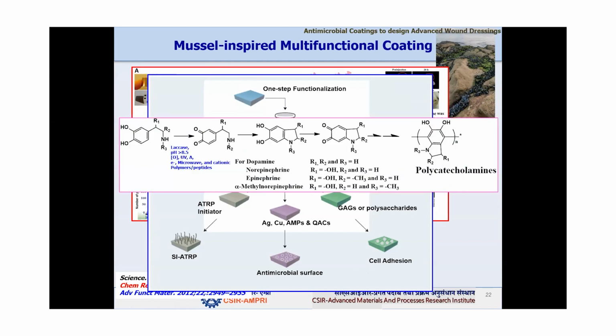And this is a simple mechanism of how dopamine and the related compounds polymerize and we get polydopamine or other related polymers. So this is the one part I have mentioned, cross-linkers: polydopamine and norepinephrine as cross-linkers. As I mentioned, they are very good coating materials. So we thought, why not use these coating materials for nanofibers? Because wound dressings can usually be easily designed by the electrospinning technique.